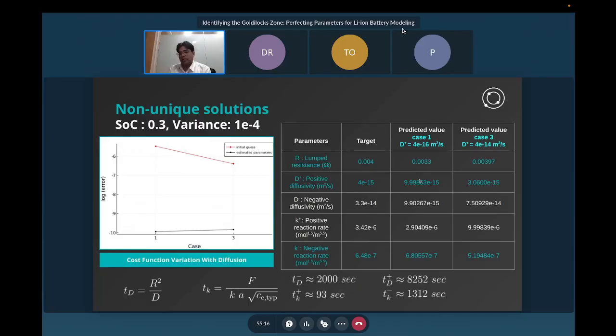And also a bit more insight into why we were having huge variations in our estimated parameters with the different initial guesses. What we saw was that the diffusion at the negative electrode and the positive reaction rates were very insensitive to the voltage response. So we tried varying these parameters and we could see that the voltage response was not changing.